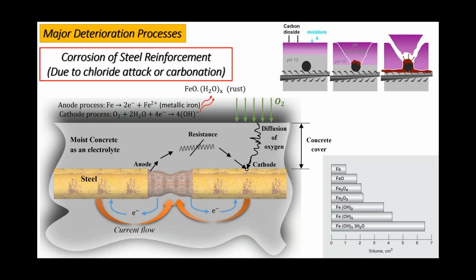Also, in the vicinity of the reinforcing steel, concentration cells may be formed due to difference in the concentration of dissolved ions, such as alkalis or chlorides. So the corrosion is going to happen through the chloride attack or the carbonation. When the level of carbon dioxide in the surface reaches the rebar, it's going to reduce the pH level of the concrete, and eventually it's going to induce stress onto the concrete surface, tensile strength, and eventually it's going to crack the concrete.